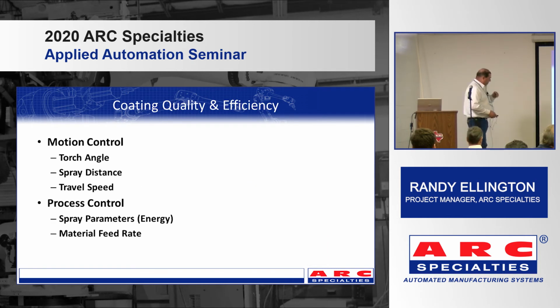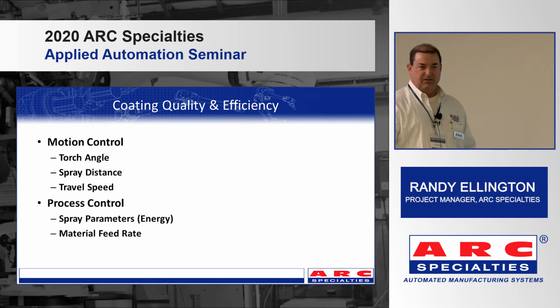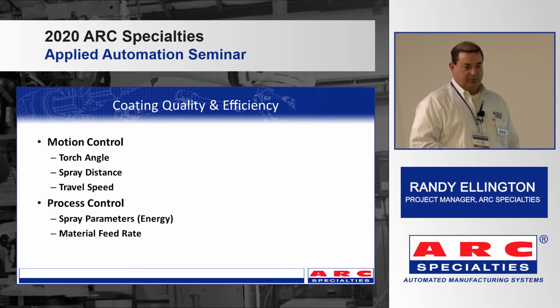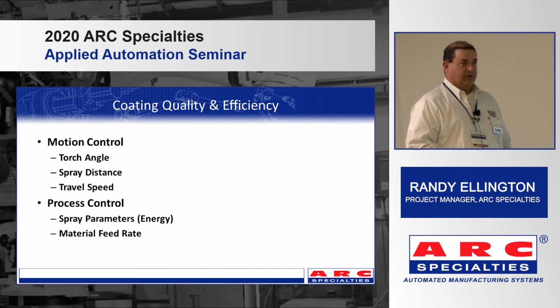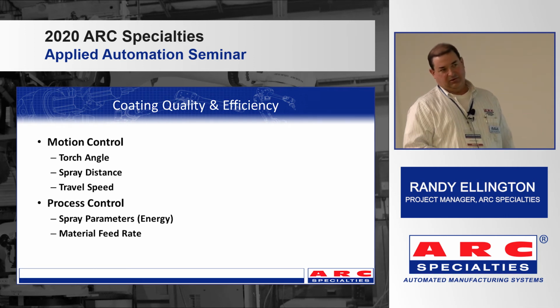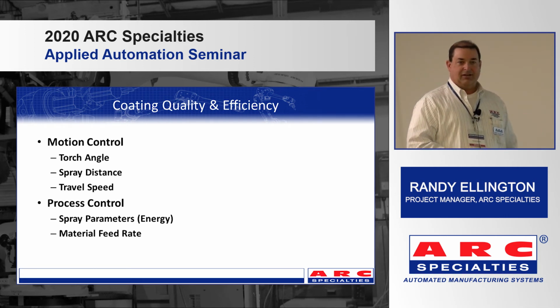All right. I kind of got ahead of myself a little bit earlier, but when you automate and put this on a robot, then you have really good, precise motion control. You can maintain your torch angle, your spray distance, and your travel speed. With most of your thermal spray processes, your deposit efficiency is typically 50, maybe 60%. Some of them are up in the 70s. But put that in perspective: if you're spraying a carbide powder that's roughly $75 a pound, with HVOF you're spraying somewhere in the 10, maybe 12 pound per hour range, and only half of it is sticking to the part. It's a problem.